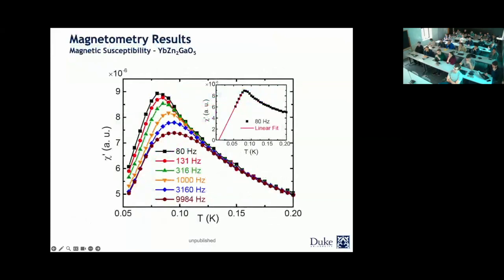Now, if we have a state that does not order, it doesn't necessarily mean we have a quantum spin liquid. It could also have a spin glassy nature, right? So another way to look at that is AC susceptibility measurements. Part of this data was collected at MagLab, and part of it we were able to collect at Duke. So this is the real part of the AC susceptibility as a function of temperature, and you can see the data extends down to 20 millikelvin, even further down in temperature.